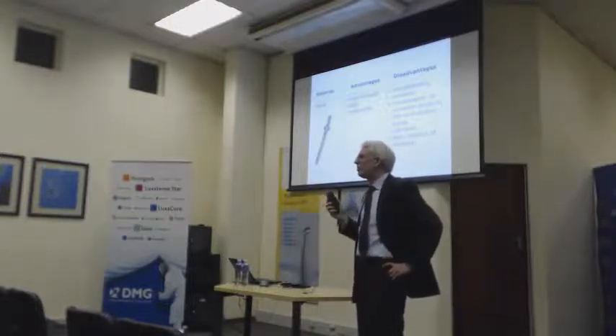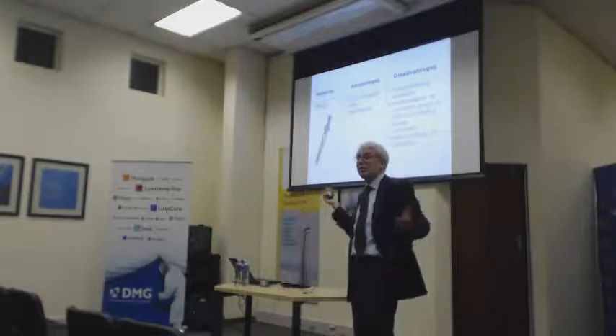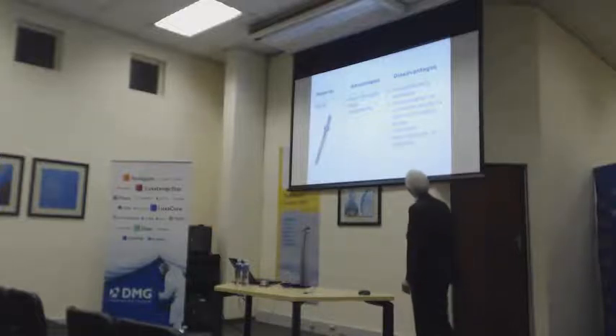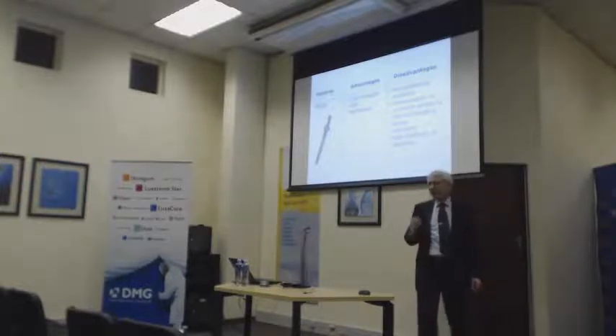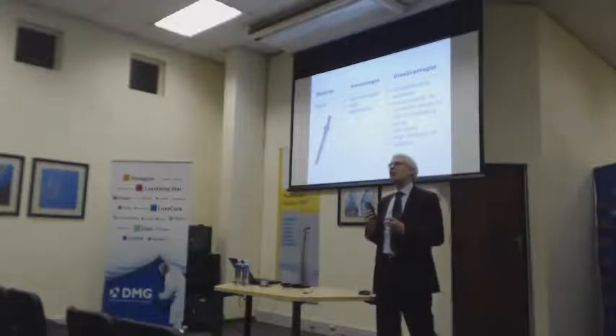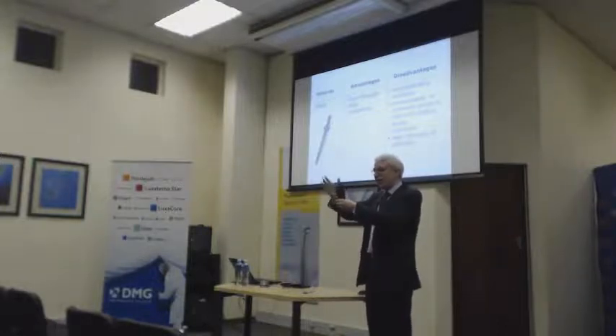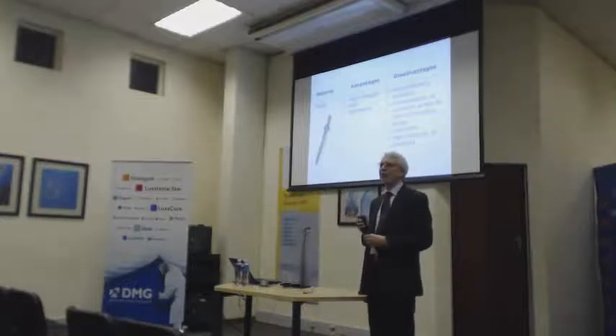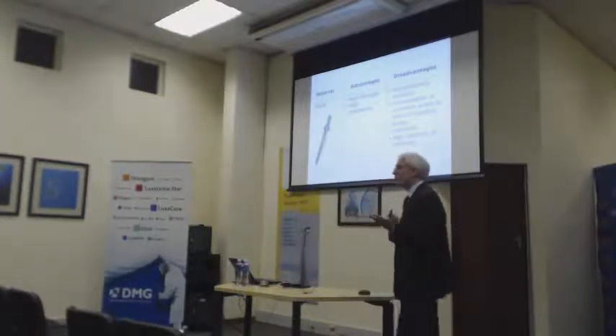Sometimes stainless steel will corrode. The oral environment is a very, very harsh environment. It's so corrosive. This is the reason why we're using gold alloys and such, because otherwise corrosion is very common. But the main disadvantage here is the high modulus of elasticity, which means that it's very stiff. So what happens if you put a very stiff post into a root canal and then load it with a force? The force is transferred directly to the tooth and you can crack and fracture the root. Again, this is not what you intended to do. You wanted to conserve that tooth.